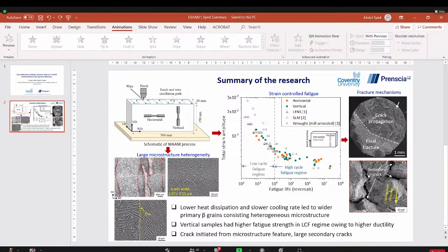So I don't think residual stress is the main concern in these builds, but when we extracted the compact tension coupons, we did see some localized stress concentration at the EDM notches that resulted in initially marginally higher crack growth rate in those regimes. However, we are also running a parallel program applying a stress relieving treatment, to see whether there is any impact of residual stresses between the as-built and stress relieved conditions. Then we will be sure whether we really have any residual stress impact, or whether it is purely a microstructure influence on this anisotropy.